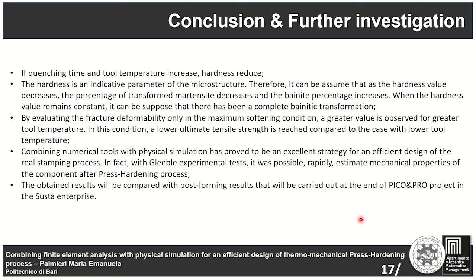Another conclusion we can draw is this. In particular, the combination between numerical tools with physical simulation test has proved to be an excellent strategy for an efficient design of the real stamping process. In fact, with Gleeble experimental test, it was possible to rapidly estimate mechanical properties of the component after press-hardening process. Finally, the obtained results will be compared with post-forming results that will be carried out at the end of the Pico and Pro project in the SUSTA enterprise.